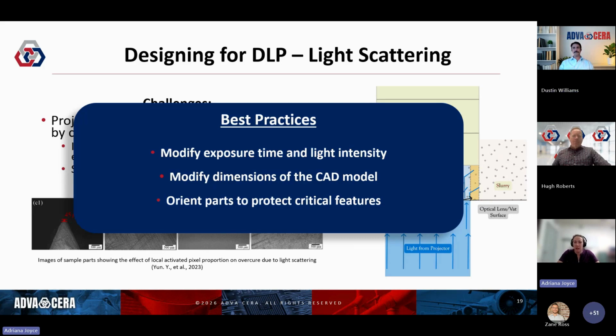And if it changes a little bit with individual features, it's the iterative process of additive manufacturing. But because we can iterate several times on the same build plate, it's very easy to iterate through green models. We can put 3 different sizes on one build plate and figure out exactly what overpolymerization each feature is experiencing, and find it out all when one print finishes instead of having to wait for the part to go through the entire sintering process.